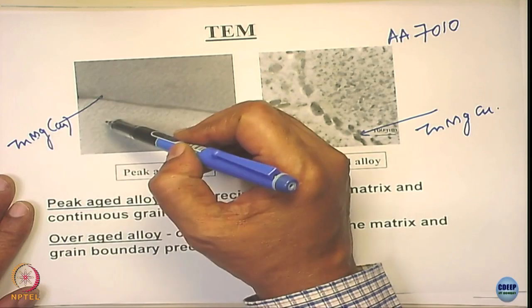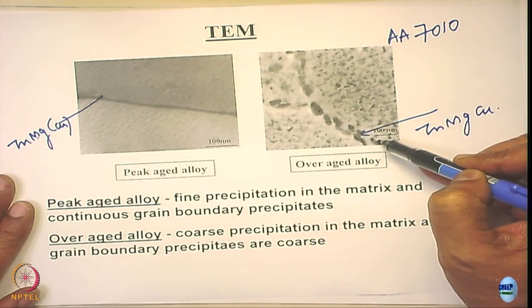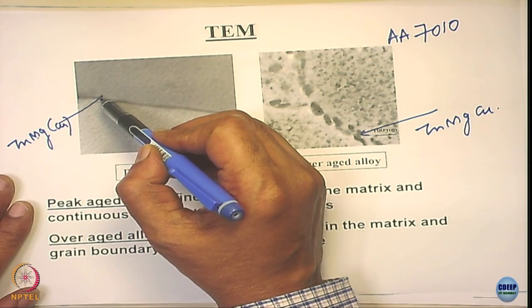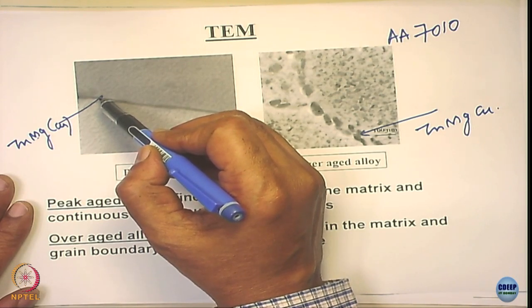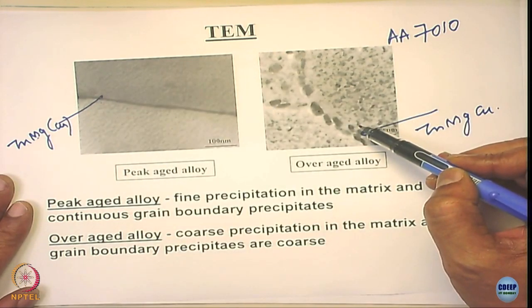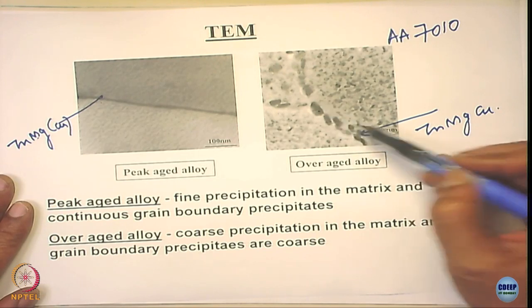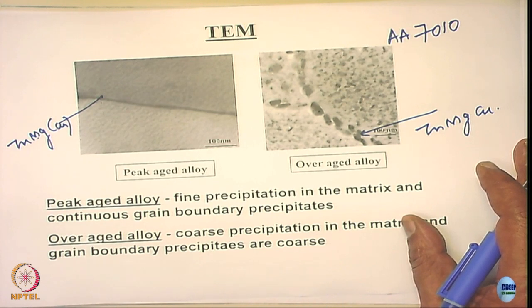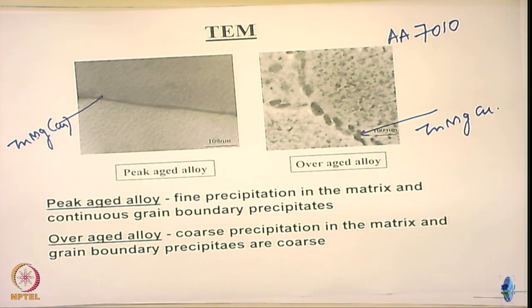In this case, the precipitates become active compared to the matrix. That means they can undergo selective dissolution here. There is no selective dissolution taking place here. So, intergranular corrosion occurs more in the case of peak aged alloys as compared to the overaged alloys. I hope you understand the point, right? Now, the problem that happens here is that when they are pancake structures,